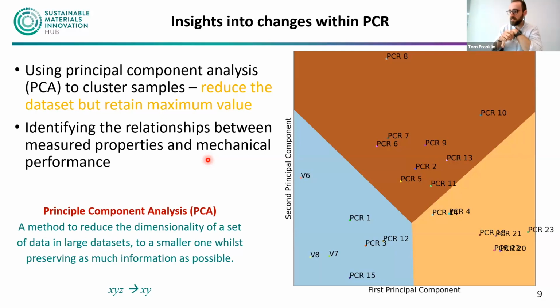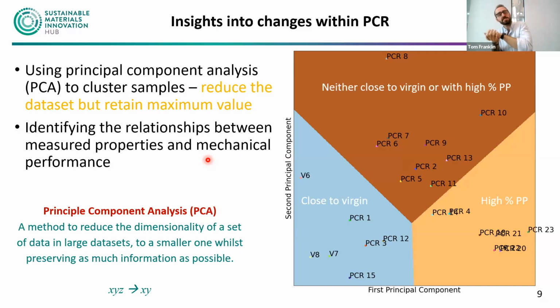And polypropylene has a really detrimental effect on the mechanical properties, so we want to try and minimize that as much as possible. But in this case, we can cluster into 3 different groups. So this light blue one, we have a group of resins that are closest to virgin polyethylene. We have our high polypropylene content cluster here in the yellow. And then our third cluster is resins that are neither close to virgin and neither have a high polypropylene content. They are unique in both of those principal components.